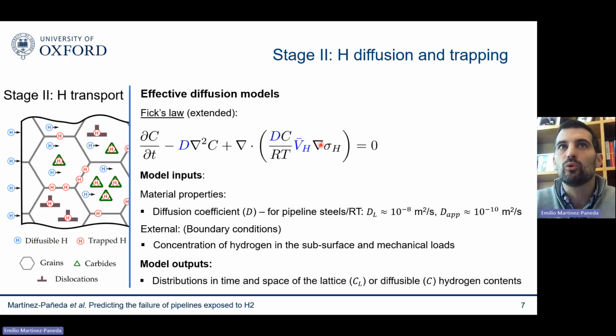And again, I'm highlighting in blue the material properties. As you can see, the only inputs the model needs are the diffusion coefficient, either lattice diffusion coefficient if you're modeling lattice diffusion, or the apparent or effective diffusion coefficient if you're looking at effective concentration, so diffusible hydrogen concentration. Again, these are two parameters that are very well known. There's no uncertainty here. We know what is the value of all the inputs of the model before we run the simulation. So there's no calibration, no fitting. Everything is pretty clear from the beginning.